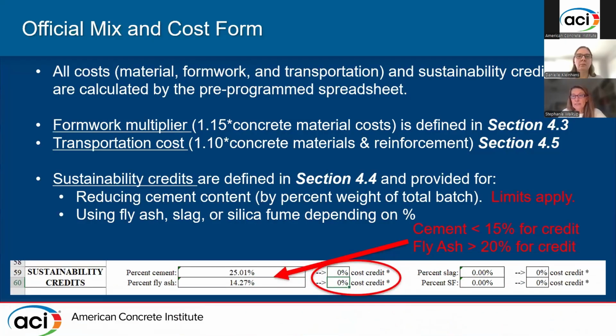For cement values less than 15%, you will receive a credit for your cost. For fly ash greater than 20%, you will receive a credit. So you can see here that while there is 25% cement content, we don't meet the 15% requirement for credit, and you'll receive 0% for your sustainability. Again, because the fly ash was used but not in significant quantity, there is no sustainability credit applied. If these values were less than 15% or greater than 20%, you would see the cost credit calculating in the spreadsheet.